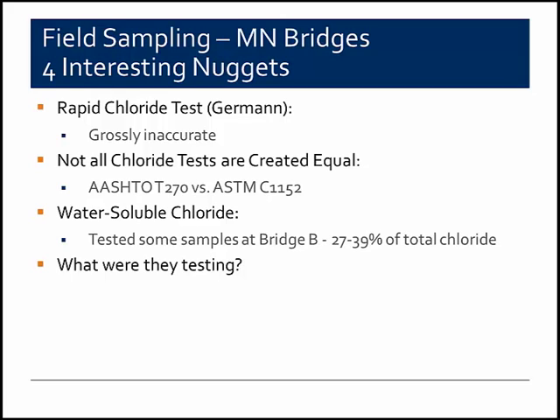In addition, in terms of chloride content, at the start of the field sampling program, there was some discussion on what is the proper chloride test to run. There was a thinking on the part of Sika that because we were sampling bridge structures, the AASHTO chloride test would be appropriate, which is AASHTO T270. And that test involves chloride analysis of a 3-gram sample. Through some internal discussions with the folks in our Janney Technical Center, it became pretty apparent to me pretty quickly that although a fine test, the AASHTO T270 test will lead to much more variable results. It's just simply not as accurate as the ASTM C1152 test.